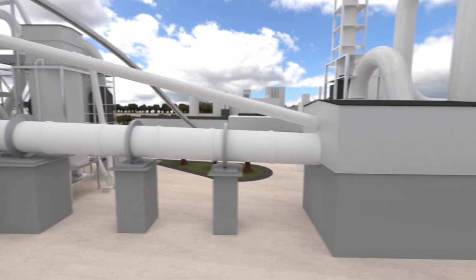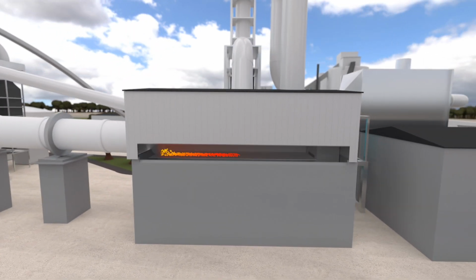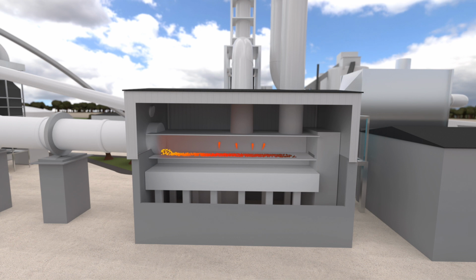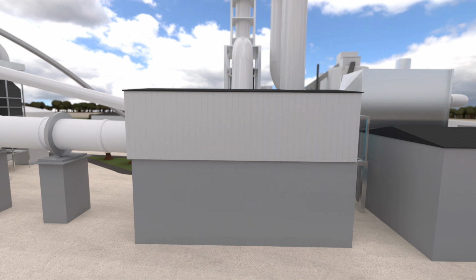At the kiln exit, we obtain artificial stone called clinker, which is rapidly cooled in a grate cooler. This cross-flow heat exchanger lowers the temperature of the clinker to approximately 100 degrees and heats up the air used for combustion, a process that helps reduce energy consumption.